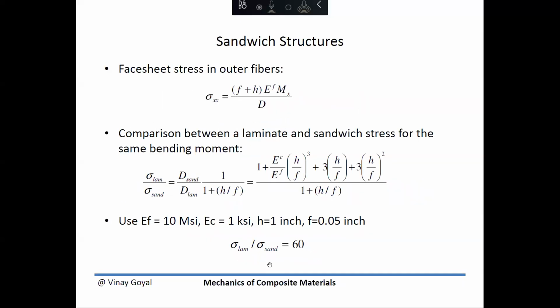So I can also look at the face sheet stress in the outer fibers. You will see that the face sheet stress in the outer fibers is also affected. If I were to calculate the laminate stresses compared to stresses for a sandwich structure, the laminate will have much higher stress than if I were to have a sandwich structure, because I have more bending resistance. Therefore, for sandwich structure, you will see less face sheet stresses as well. And I invite you to go through the calculations for the face sheet stress, which can be calculated with this formula, and then compare the laminate versus the sandwich by taking this ratio.